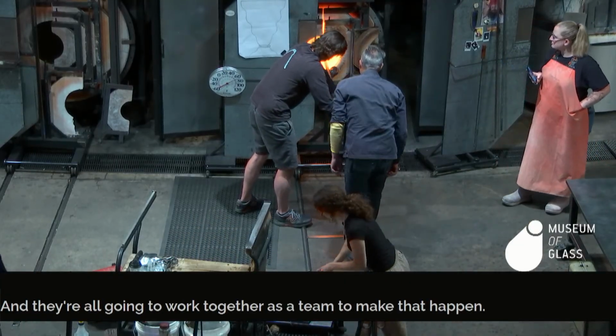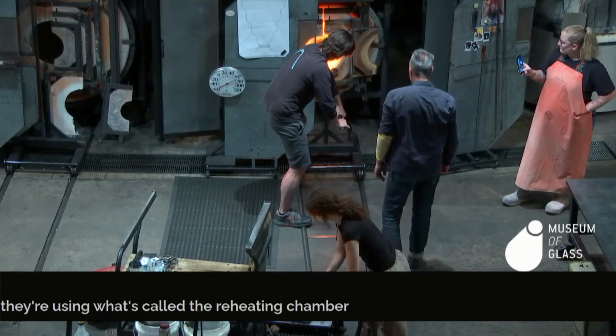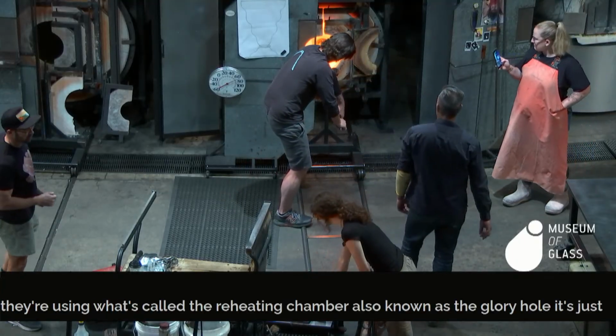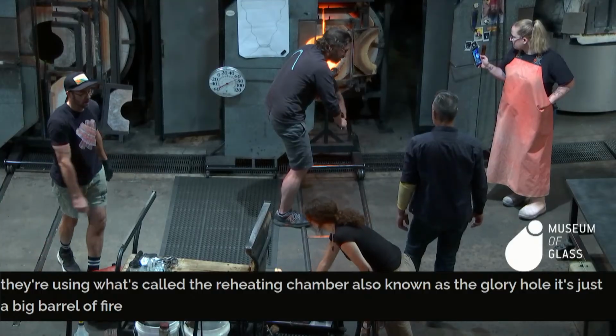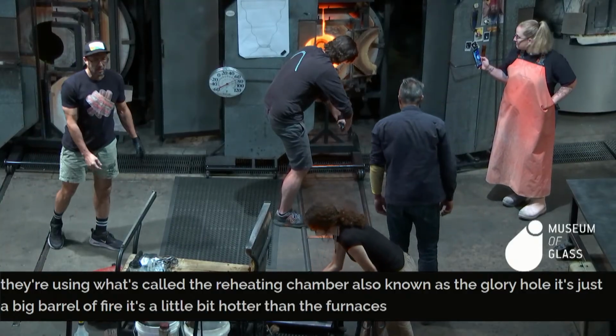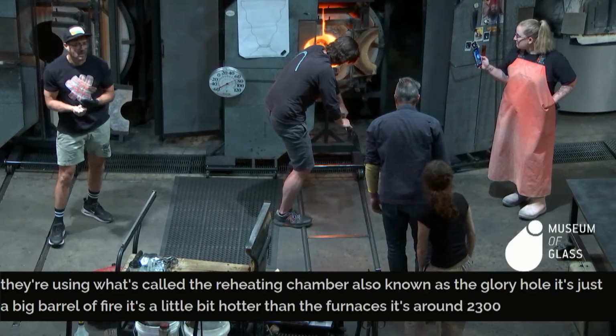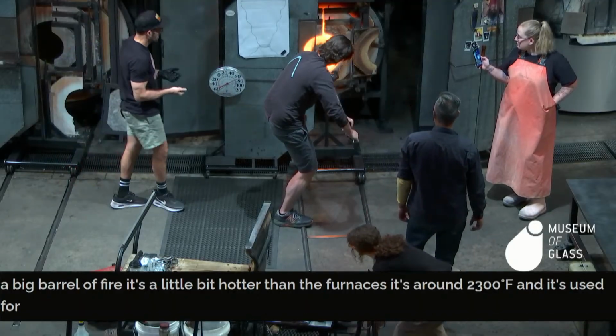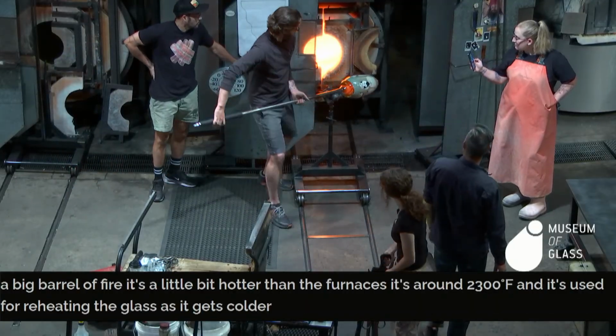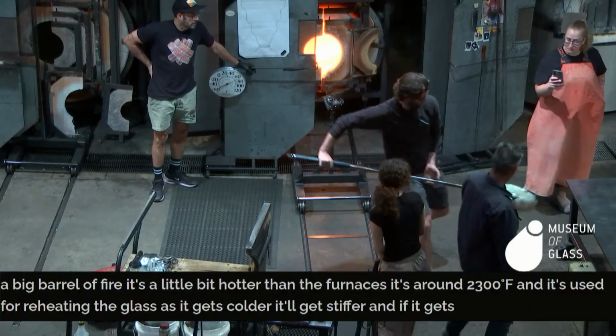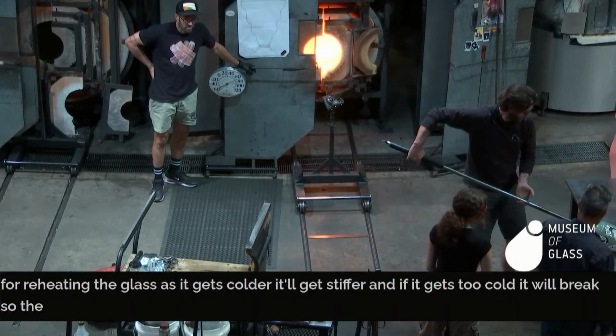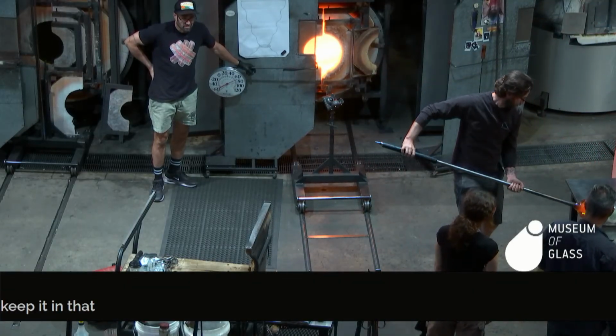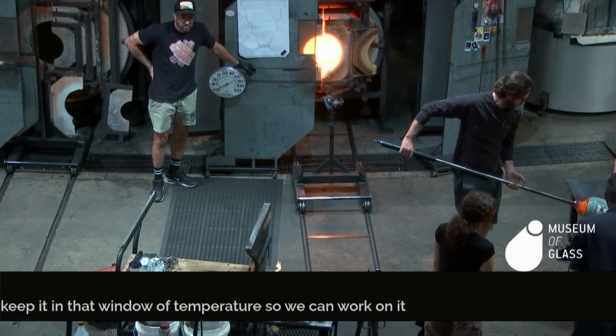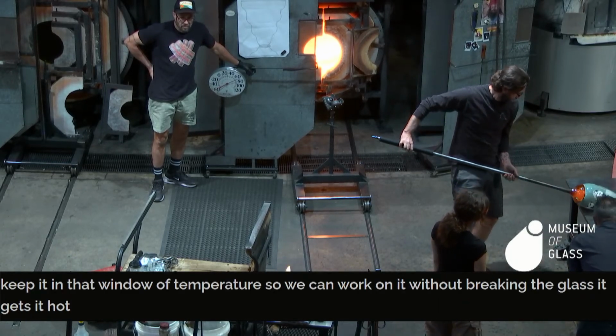They're using what's called the reheating chamber, also known as the glory hole. It's just a big barrel of fire. It's a little bit hotter than the furnaces. It's around 2,300 degrees Fahrenheit, and it's used for reheating the glass. As it gets colder, it'll get stiffer, and if it gets too cold, it will break. So the reheating chamber helps us keep it in that window of temperature so we can work on it without breaking the glass. It gets it hot so it's malleable.